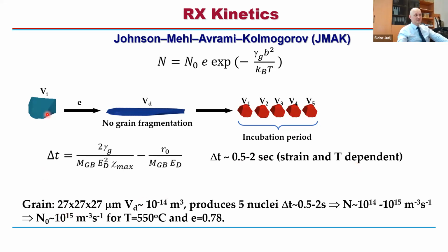So if you have an initial grain with the average grain size of 27 micrometers, I calculated the volume, so the volume of the initial grain and deformed will be identical, and then assume that this grain will produce 5 nuclei within this period, 0.5 or up to 2 seconds. Then I get the nucleation rate. I put all these parameters here, right? So then I get nucleation of 10 to the power 14, 10 to the power 15, right? So N0, I calculate back. If I know the N, I can estimate the N0. And it turned out that in fact N0 is approximately 10 to the power 15 for 550 centigrade and strain